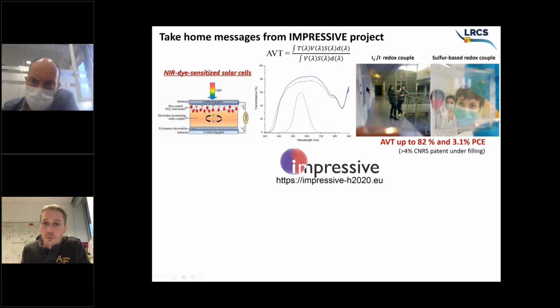So we need to develop a dye which does not have this shape here, which is still related to the H aggregation. So we have to shift the singlet transition of the dye by 20-30 nanometers in order to make it completely color neutral, because this sulfur-based redox couple is totally transparent and colorless.